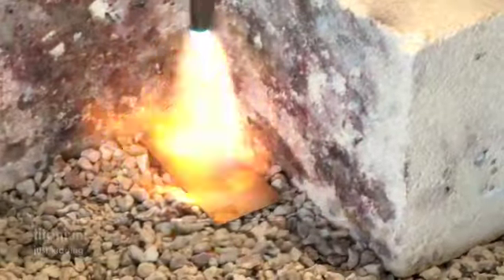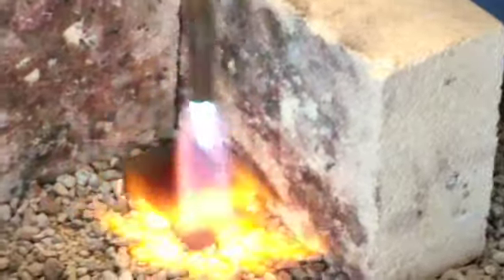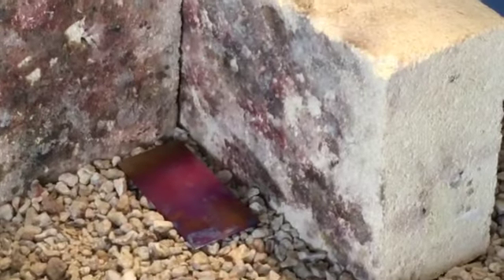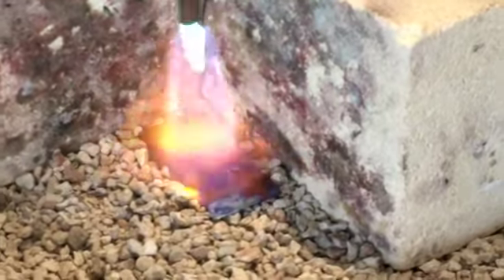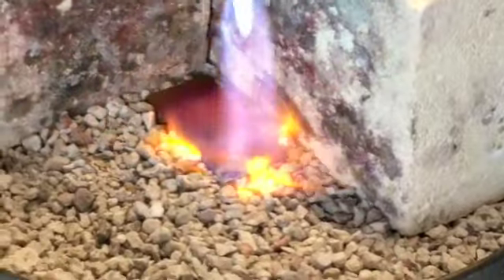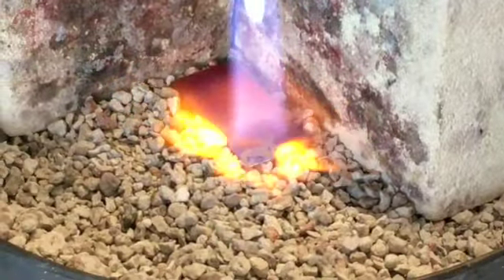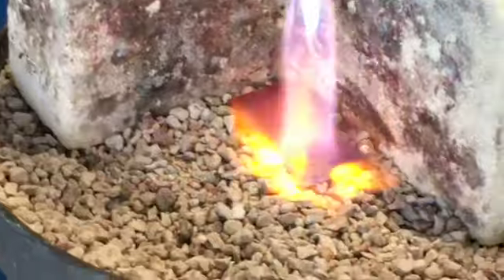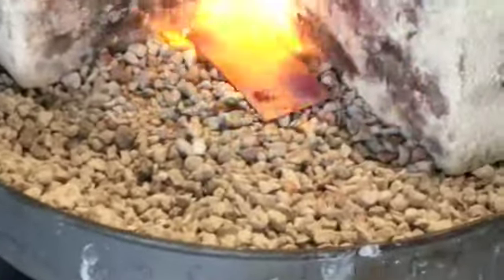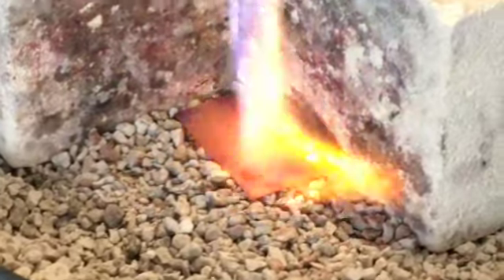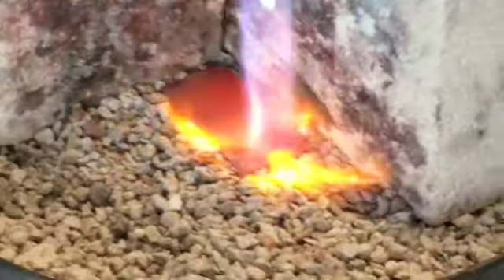Titanium cannot be annealed in our shop. Even the acetylene torch is not hot enough to get it to its annealing point, and it forms tough but colorful oxides that can't be easily pickled off. It can also ignite if you did manage to get it hot enough, and it's impossible to extinguish a titanium fire without special equipment. Fortunately, titanium work hardens extremely slowly, and you are unlikely to need to anneal it anyway.